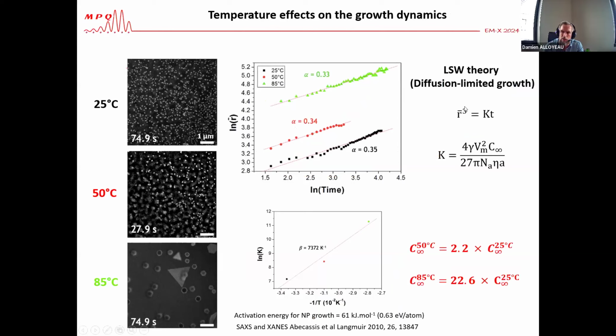And you see that the cubic radius of the growth trajectory varies linearly with time. And that's what you expect when you have a diffusion-limited growth. And in that case, what is interesting is that the growth now depends only on this growth constant, K.